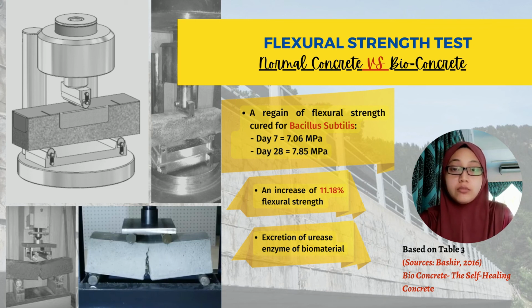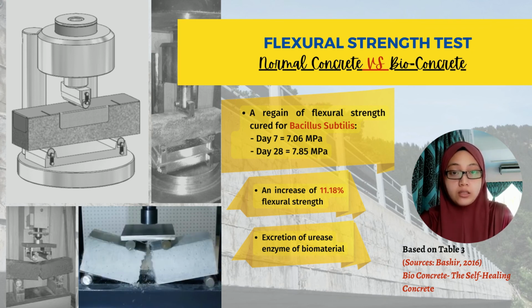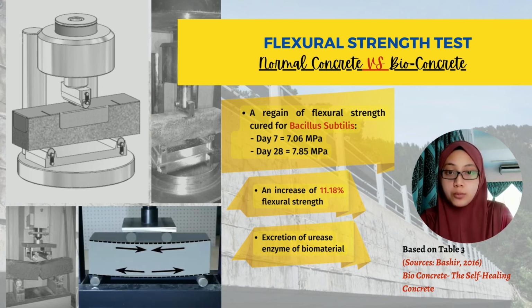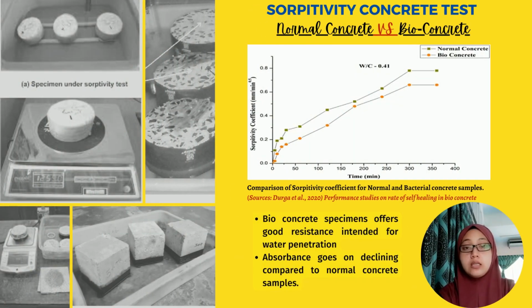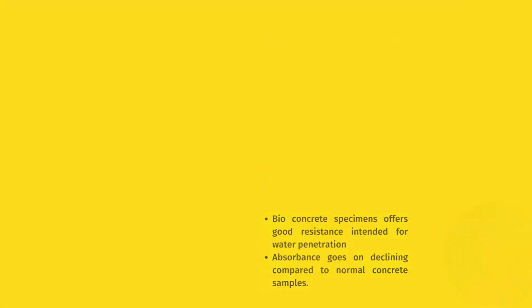There is an increase of 11.18% of flexural strength after 28 days of curing by the excretion of urease enzyme of the biomaterial. Sorptivity test is an indirect measure of permeability of concrete. It is to monitor the water penetration resistance of the concrete. It resulted that the bioconcrete offers more resistance against the passage of water into the concrete, hence the porosity decreases. The precipitates produced by the bacteria in the pores of the concrete improve the denseness of the concrete specimens, which leads to decreases in sorptivity values.